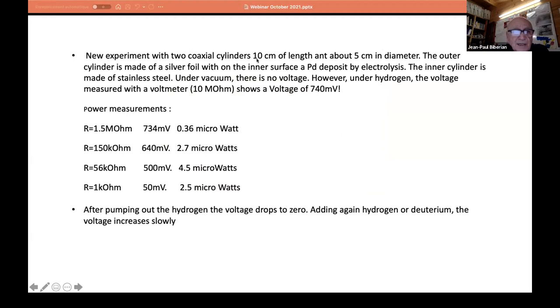Now the cylinders were about 10 centimeters in length, 5 centimeters in diameter. The outer cylinder was made of silver, with palladium deposited by electrolysis. What I get now is a lot more voltage. Look at that, it goes up to 734 millivolts. Then if you change the loading resistor, the voltage decreases, but you go to a maximum power of 4.5 microwatts. Before that, we had nanowatts. Now we are in the microwatts range, which is much better, indicating something is happening there.